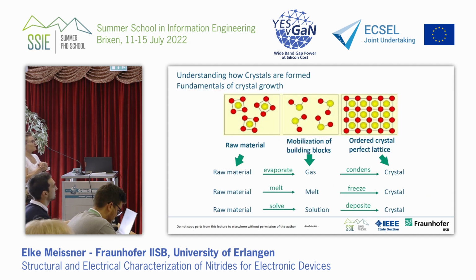So how is a real crystal formed? The fundamental of crystal growth is, if you want to have this perfect lattice, you have to order this big solid body atom by atom by atom, over a process with process conditions that you can steer, like temperature, furnace power, gas flows. So these are very rough parameters. Imagine you have very rough parameters, turning a knob and your gas flows faster or not so fast. But what you're doing in fact is, piece by piece, atom by atom, ordering a perfect lattice. So this is a big challenge.